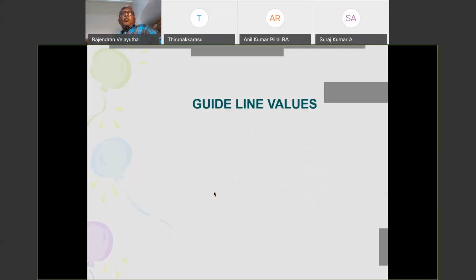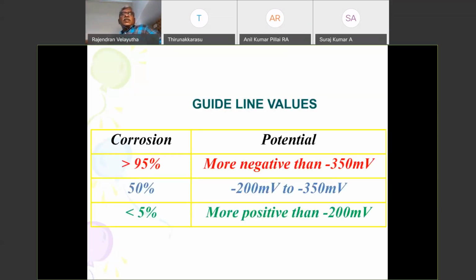If it is more than minus 350 millivolt, obviously we know that it is more negative than minus 350, the corrosion probability is more than 95%, and between minus 200 to minus 350, it is 50%, and then it is less than 5%. Here we come to the conclusion of how soon I need to take up the rehabilitation. Can I wait for some time, or is it so urgent that we need to take it up immediately? That sort of inference we can draw.